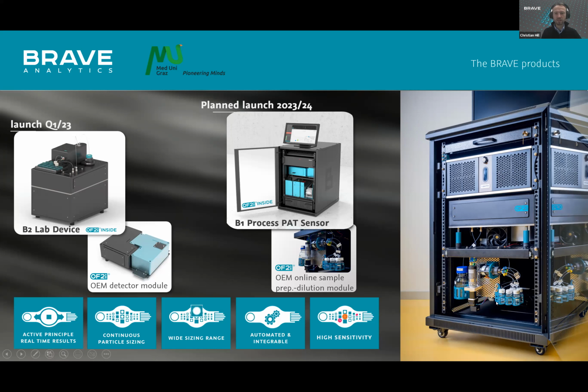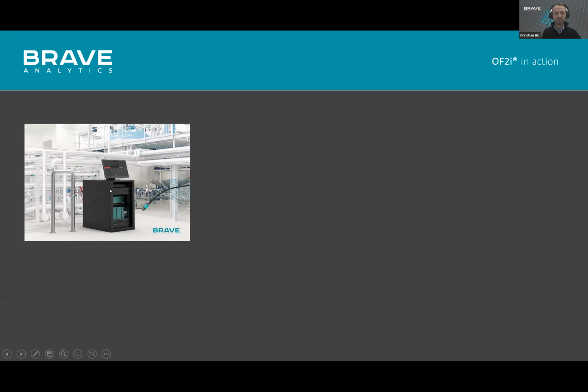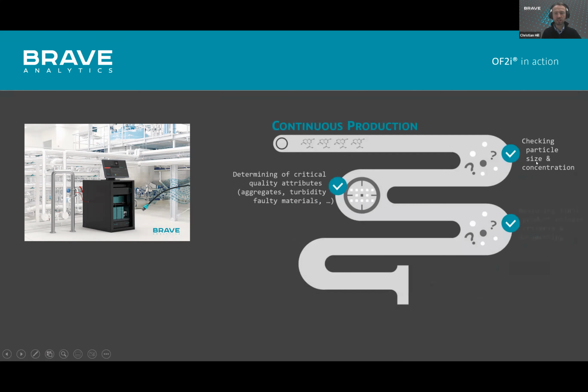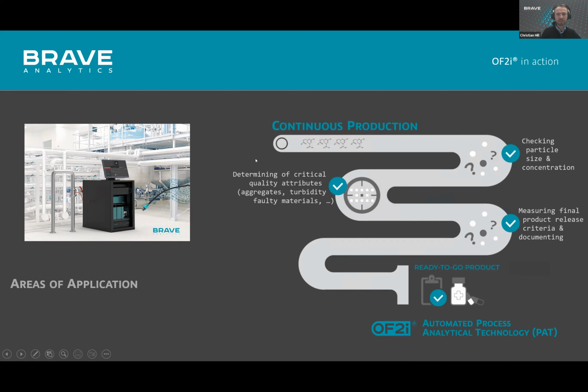You can use this as a kind of online characterization. Since concentration is always a topic, we also developed a dilution system, or sample preparation, which is then directly connected to the process line. The process line basically feeds a little bit of sample into our device. Here, the correct concentration is determined because we measure concentration, and we give back particle concentration and particle size of a wide size range, starting from roughly 20 nanometers up to a couple of micrometers. Of course, it depends on the sample, but we also go into purity measurements, turbidity, and aggregates, adding spectroscopy approaches like Raman spectroscopy on a particle basis.